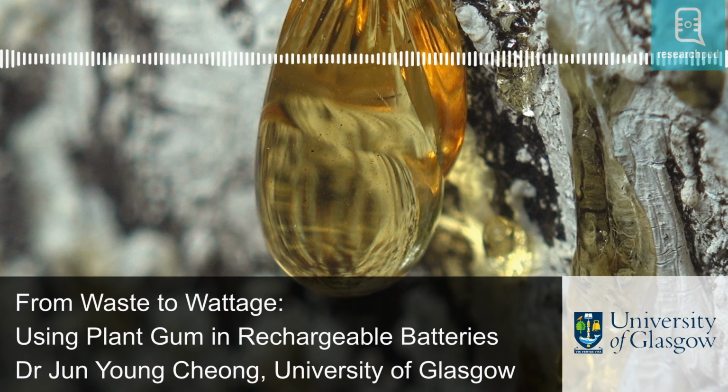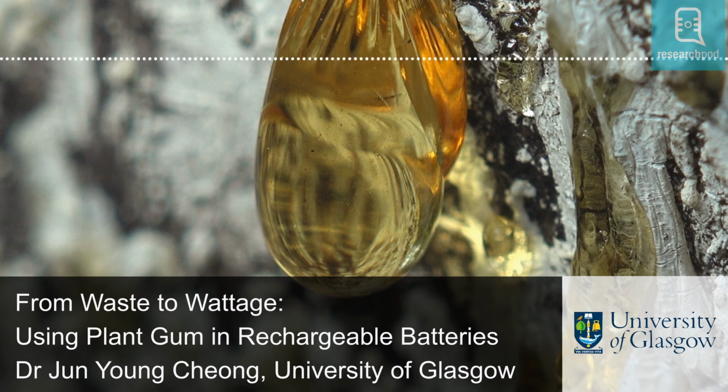Researchers began by extracting the target molecules from the tree gum. The natural graphite anode powder was then mixed with either the water-soluble or conventional binder. The resulting blends were coated onto copper foil and combined with lithium metal and an electrolyte, forming two half-coin cells. This form of cell would allow researchers to focus their investigation on the performance of the anode. Various analyses were then conducted to evaluate the anode's structural, chemical, and mechanical properties.